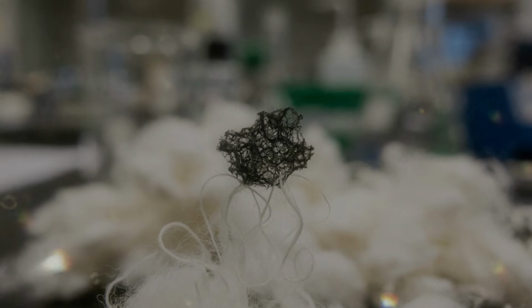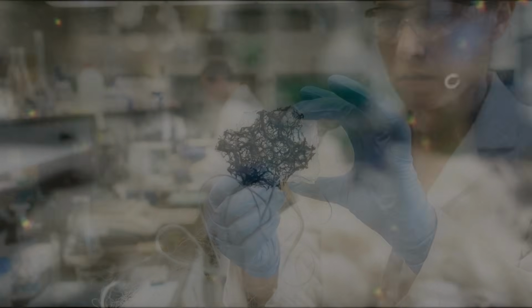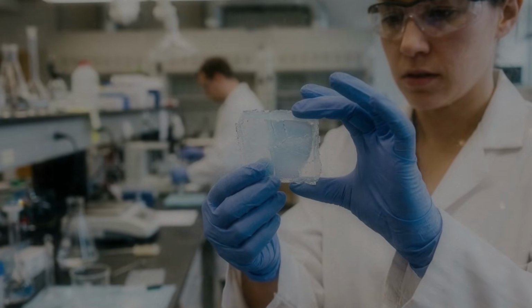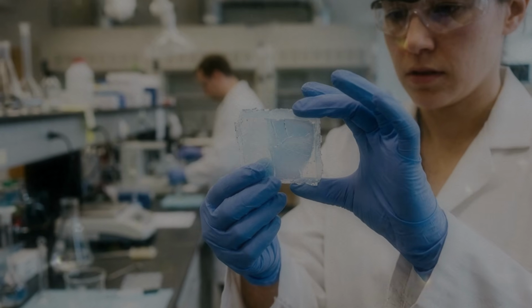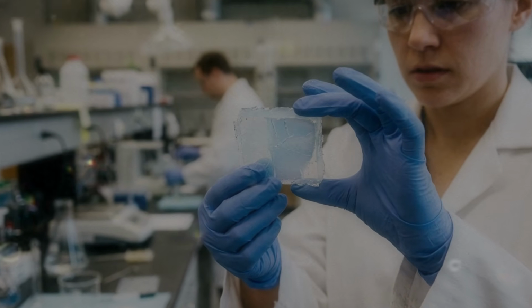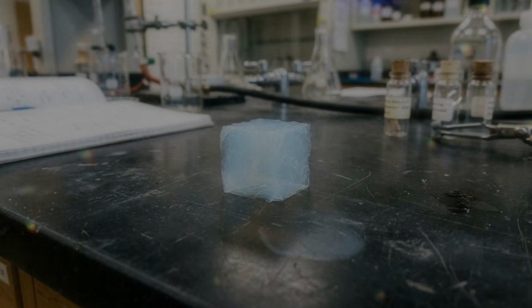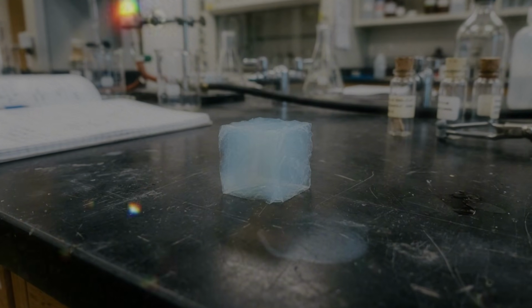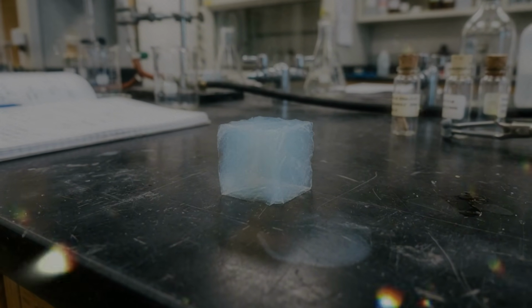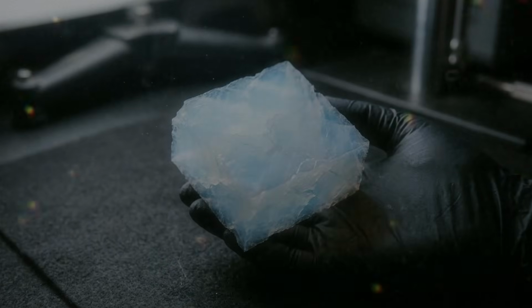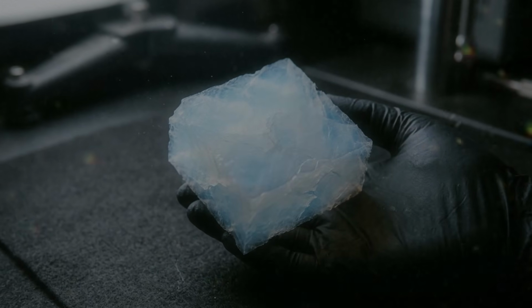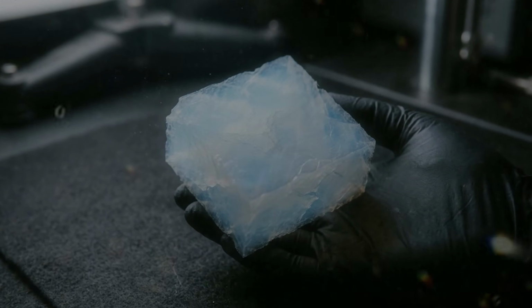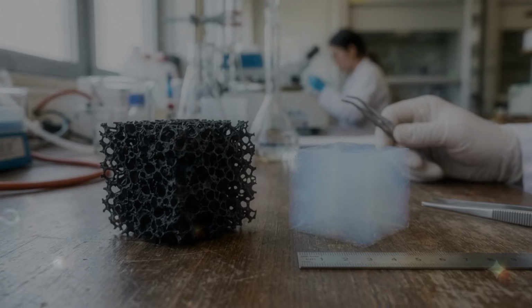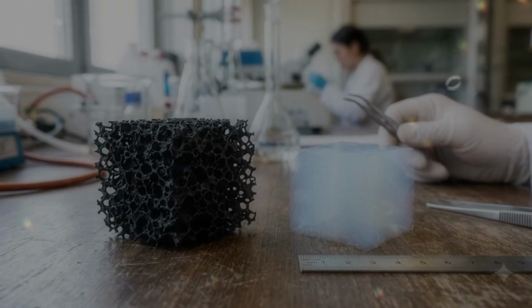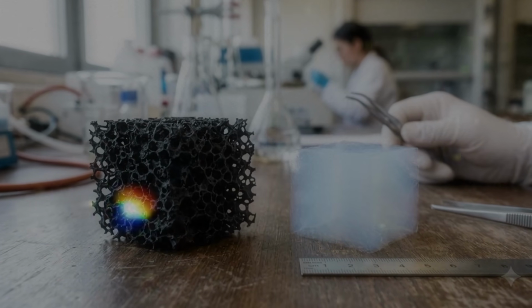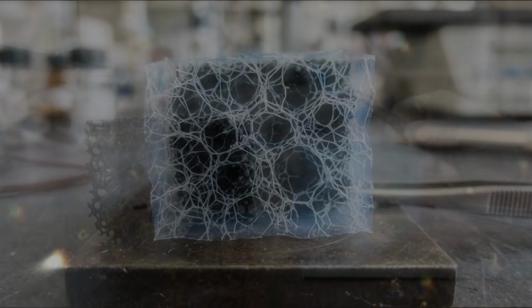Three-dimensional printing offers more direct control. A thick ink containing graphene oxide can be deposited into a planned pattern. The printed object is gelled and dried while its arrangement is preserved. Designers can create repeating beams, open lattices, and shapes that would be difficult to produce through random self-assembly. Printed graphene aerogels are generally denser than the most extreme record holders. Their strength comes from organization rather than from reaching the lowest possible mass.